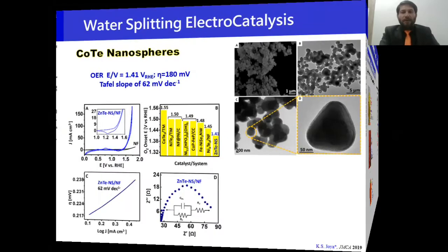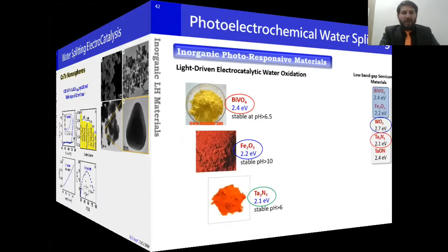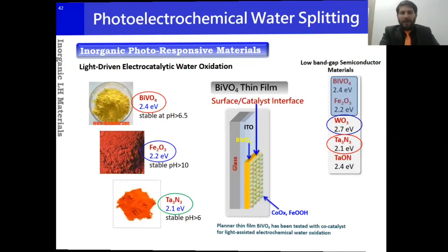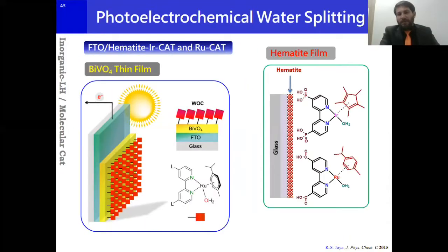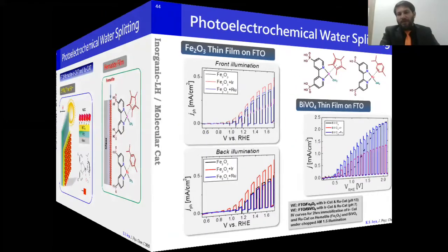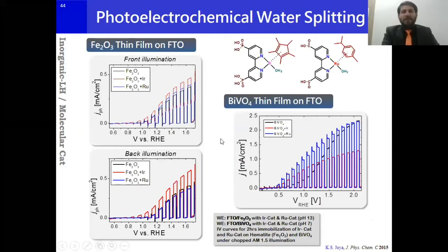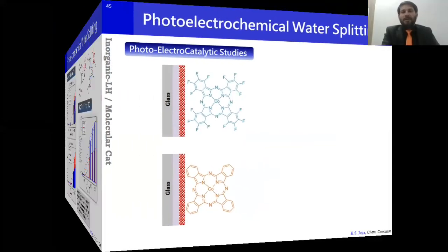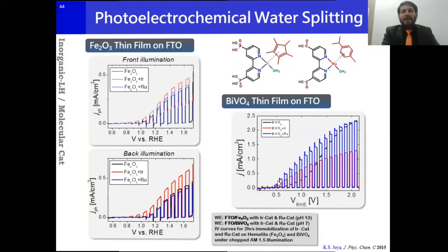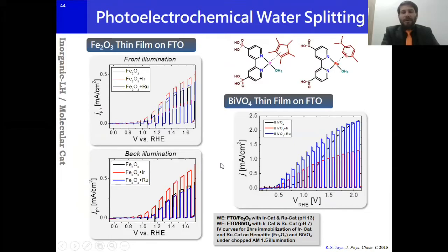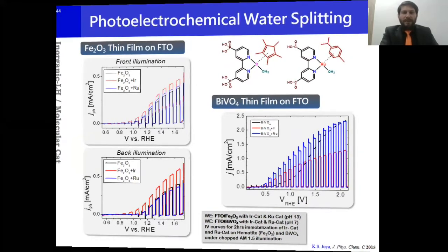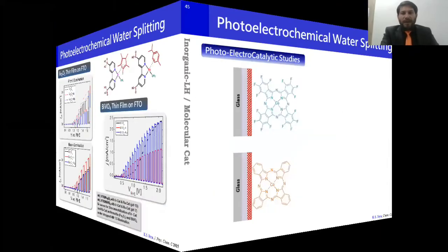So then for some photoelectrochemical applications, we developed bismuth vanadate, hematite, and tungsten trioxide. We functionalize them with molecules. In some cases, inorganic material also. And you can see, in each case, the enhancement in the photocurrent, which indicates that in the presence of the catalyst, the catalytic current can be really increased. And in some cases, even the onset potential is reduced. You can see in these cases there is a charge suppression effect because the onset is prior to the onset of the simple photocurrent compared to the catalytic photocurrent. In this case, we are using different molecules on hematite.